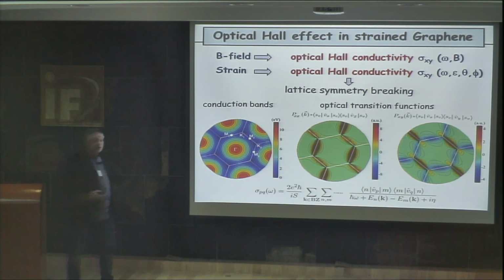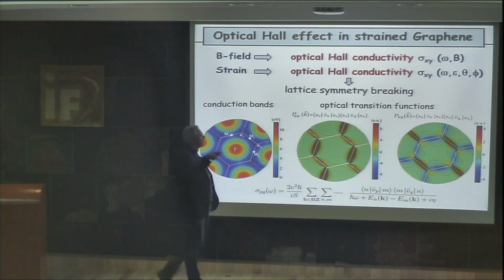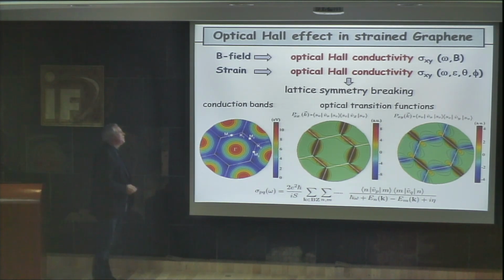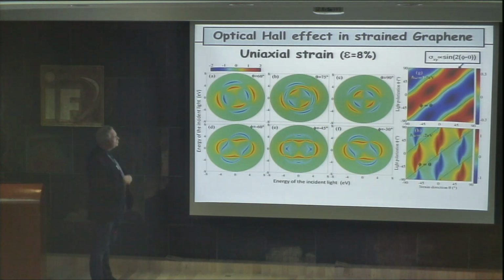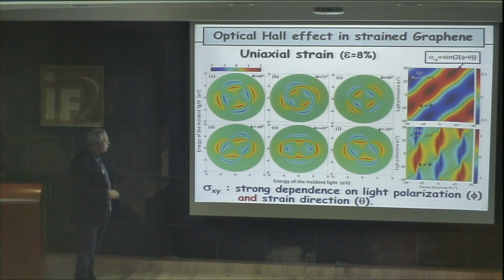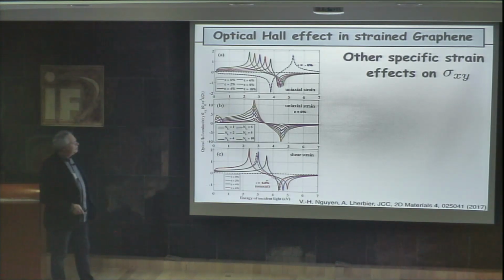So you can explain just by investigating this optical model why you have this variation in the optical Hall conductivity. We have played a lot on this model for different strain angles and different polarization angles. Sometimes we have 3 peaks that appear when we have 3 endpoints that are completely different for a certain strain direction or for a certain polarization direction. So it's clear that sigma xy is strongly dependent on both light polarization and also strain direction.